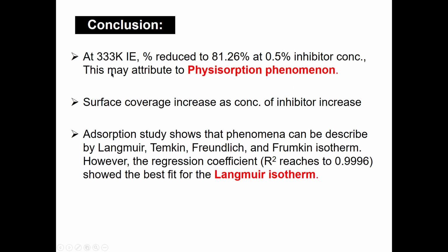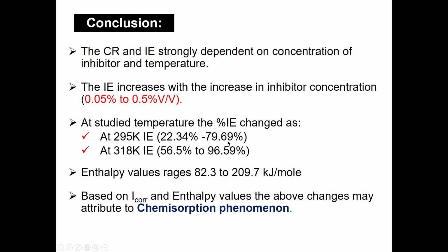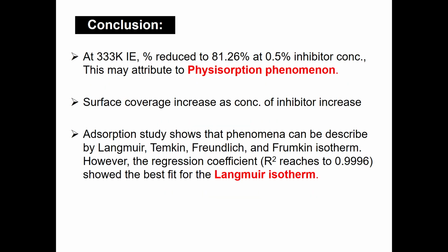While at temperature 333 Kelvin, at higher temperature, inhibition efficiency reduced, and also the enthalpy values are low as compared to the lower temperature. This shows that it is a physisorption phenomenon. And we found that the surface coverage increases as the concentration of the inhibitor increases. It is due to the presence of functional groups which are adsorbing on the surface of the metal. So the phenomenon can be described by Langmuir, Temkin, Freundlich, and Frumkin isotherms. They also fitted the data.